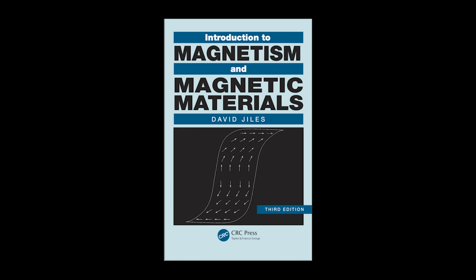That's clever. Let's go back to those fascinating materials mentioned in the sources. Amorphous magnetic fibers. They seem to be designed specifically to maximize those Barkhausen jumps. They're highly engineered materials, yeah. They're typically very thin wires, maybe 50 microns in diameter, made by rapid quenching. And because they don't have a crystalline structure, their internal stress pattern, combined with magnetostriction, is what defines their domains. And magnetostriction is? Magnetostriction is the property that causes a magnetic material to change its shape or length when it's magnetized. And how does that create this massive Barkhausen effect?